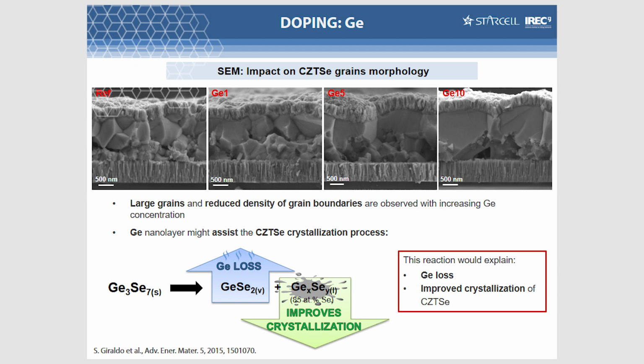So germanium can be useful for improving the VOC deficit of kesterite. Among the positive effects of germanium, we obtain really very big crystals, and at that time we proposed this model that germanium is forming some liquid phase for improving crystallization. This was just a theory, and very recently we succeeded to prove it experimentally, and we are now writing the paper to show that germanium also can act as a crystallization flux for kesterites.